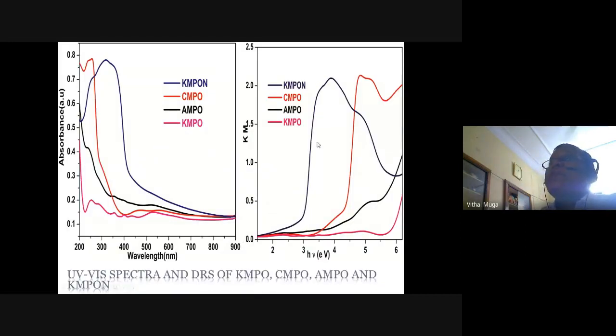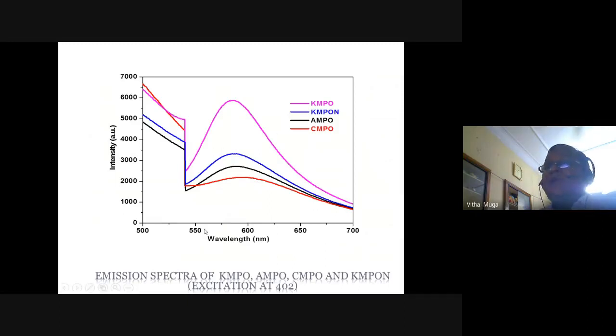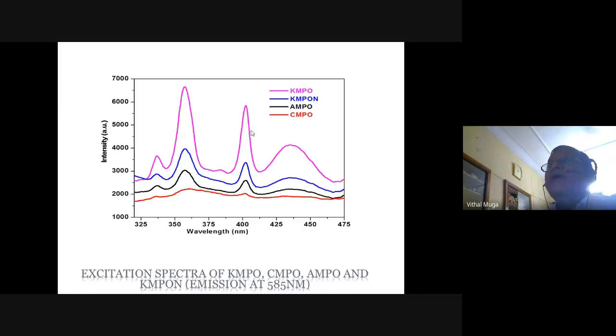Now this is how actually the band gap is tailored. Now this is the parent compound, and where is the parent compound? I think the red one. Red one is, I think, this one. This one is the parent compound, and all the other materials show less band gap energy compared to the parent material. And this is the emission spectrum. This shows that KMPO shows the least photocatalytic activity because the PL signal intensity is inversely proportional to its photoactivity.